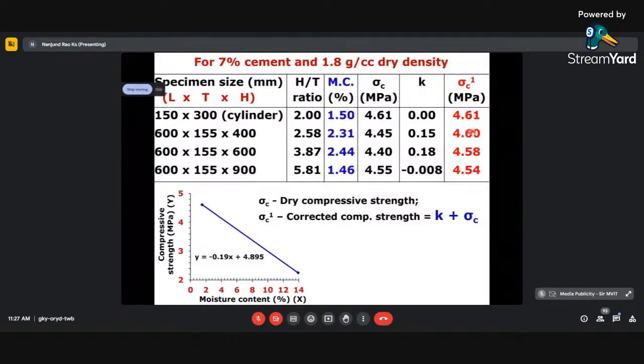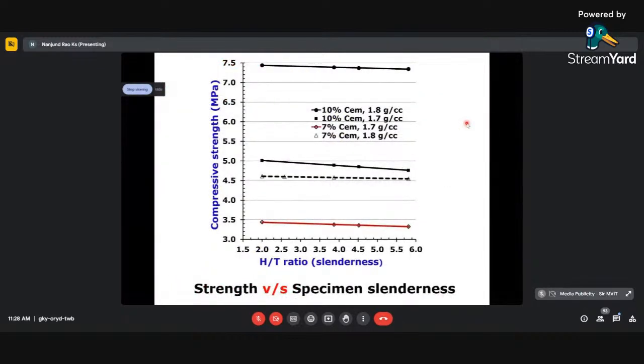Now, this is for the different specimens of different heights. What you will see here is there is no big difference in the compressive strength, 4.54 to 4.61. That means for an aspect ratio between 2 and 5.8, the aspect ratio has no influence on the compressive strength. That's what is depicted graphically here. From 2 to almost 6, the curves are flat, for both cement contents, with dry density 1.7 and 1.8 grams per centimeter cube. So up to this slenderness ratio, there is no change in the compressive strength.